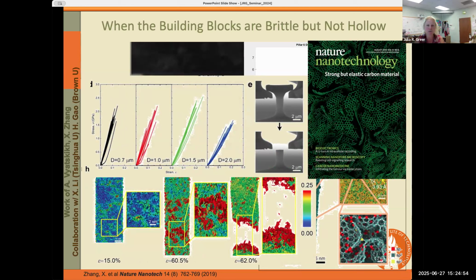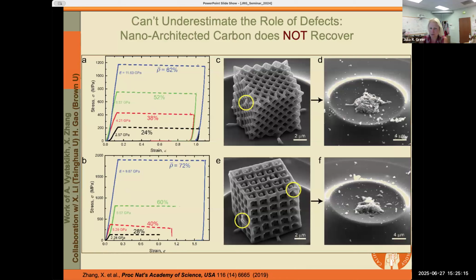And as my old advisor would say, don't believe anybody who tells you about ductility in compression. So what you see here are some tensile experiments that show that sure enough, even under tension, these carbon micropillars and nanopillars are extendable by at least 20%. All right, well, so here we are. We learned all about carbon that we needed to learn. And so at that time, we decided to architect with these carbon nanoscale building blocks, since we discovered that they were deformable. And what we learned is that we're not going to get any recoverability in these kinds of nanolattices, no matter what we did.